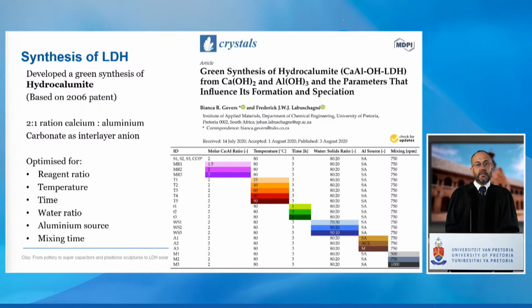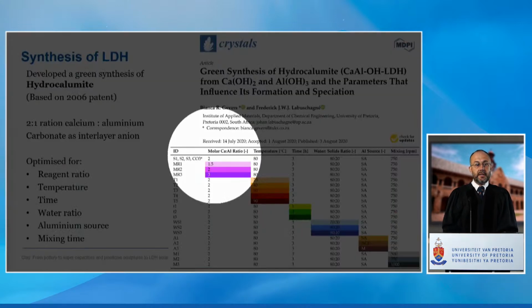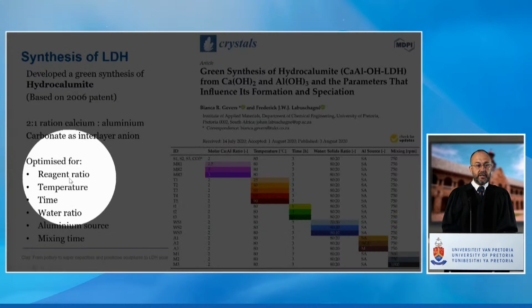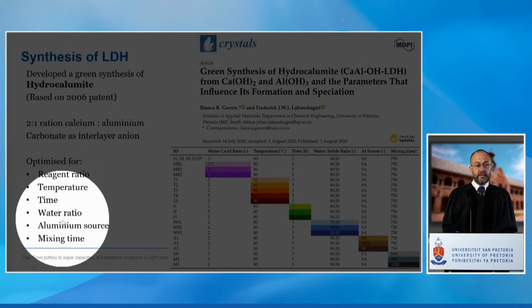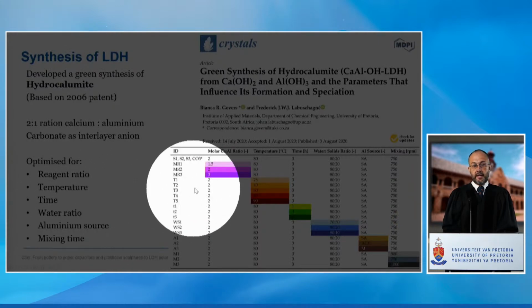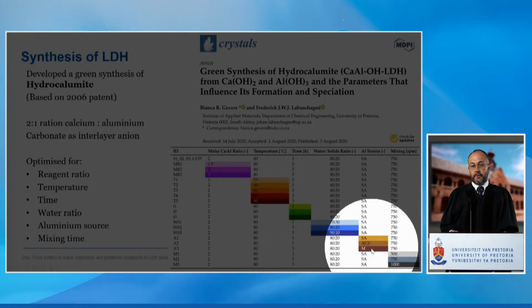We then took this technology a little bit further when I came back to the university and looked at forming hydrocalumite, another LDH, but in this case made up of calcium and aluminium with carbonate in the interlayer and not magnesium and aluminium. In this study shown on this presentation, we optimized the reagent ratio, the temperature, the time, the water ratio, the aluminium source, and the mixing, as indicated in the table.